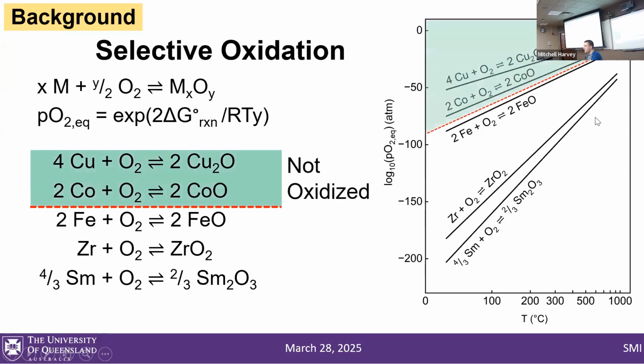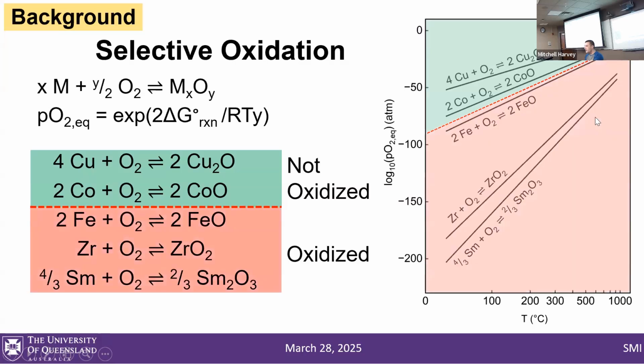Any metal above that line is not going to oxidize. It's going to stay as a metal because there is not enough oxygen in the atmosphere to thermodynamically oxidize those metals. And then any metal below that line is going to oxidize—there's enough oxygen to oxidize them. And the placement of this line, I just said we're going to place an arbitrary line on the graph, but the placement of this line is very important.